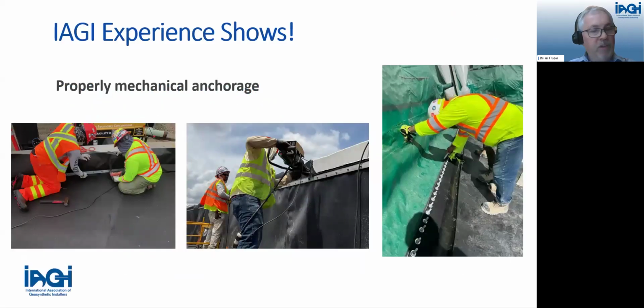Also, mechanical anchorage we see on a lot of containment systems. It's really important that we use proper clamping, proper anchoring, and proper sealing to create, in many cases, a watertight connection below the fluid level, as well as where we are supporting or anchoring the geomembrane system above the water level. With mechanical anchorage, we're normally using stainless steel batten bars, neoprene or EPDM gaskets, and stainless steel bolts, and we need to ensure we're using proper torquing pressures, etc. In new concrete applications, we will often put in polymer or plastic embedment strips that we weld to. The photo on the left is a ring berm of a tank farm, inside the tank berm, and we're doing the mechanical anchorage there.